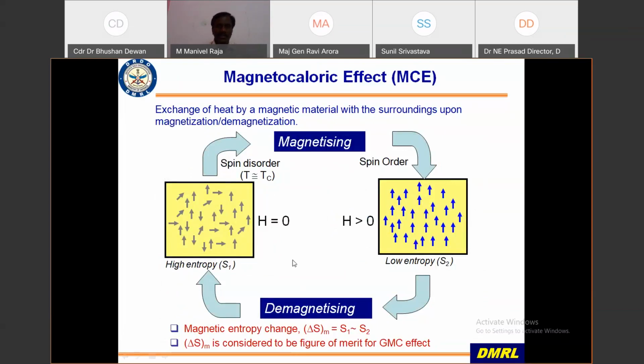When this magnetocaloric material is exposed to a magnetic field, it is heated up. That heat is removed by circulating water. Then you remove the magnetic field, and it goes back to the disordered state. Then it takes heat from the surroundings, and as a result, it gives the cooling effect. So that is the principle of the magnetocaloric material.